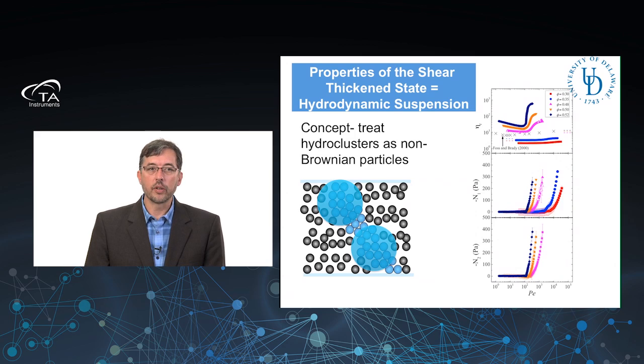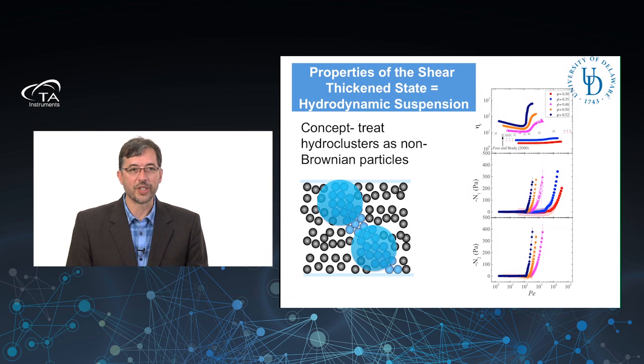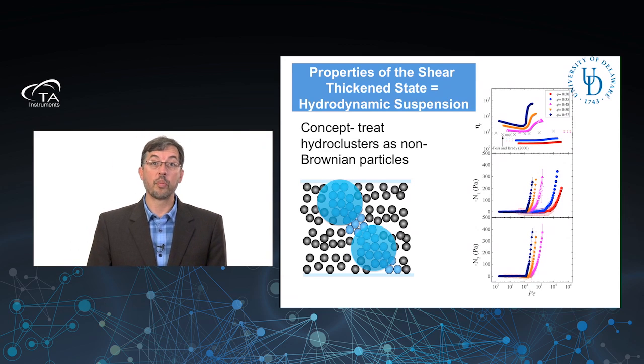And they're fairly small in the big scheme of things. They're on the order of hundreds of pascals in the shear thickening regime, and they're negative. And they're about the same order of magnitude. That's very, very different than polymer systems where N1 is generally large and positive, right? So here you see the effects of hydrodynamic interactions show up as a large negative N1, okay? And that's been predicted from theory and seen in simulation and is shown here in experiment.